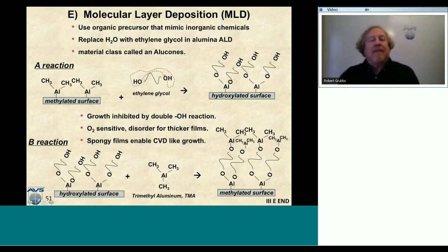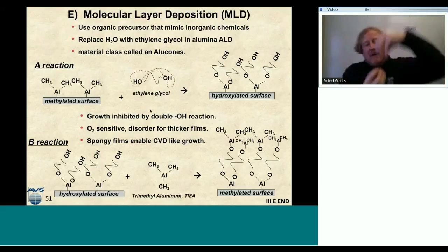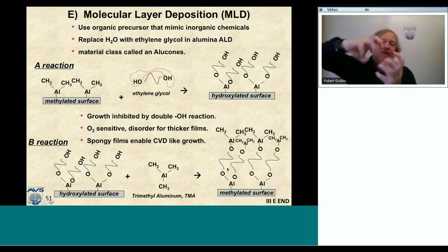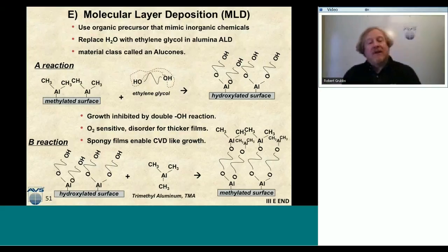These bonds can also be sensitive to oxygen, and as you grow these films, they become a little more disordered and start to tip over, and they don't really grow in this bond, because of the degrees of freedom of rotation that those organic molecules have. Also, these films are low density and spongy, so precursor can absorb into this sponge of the organic network, and then I can get this CVD film to grow. So this area has its challenges, but I still find it very exciting because it's a combination of both organic and inorganic chemistry. So that ends the atomic layer deposition section, at least the chemical part of it.